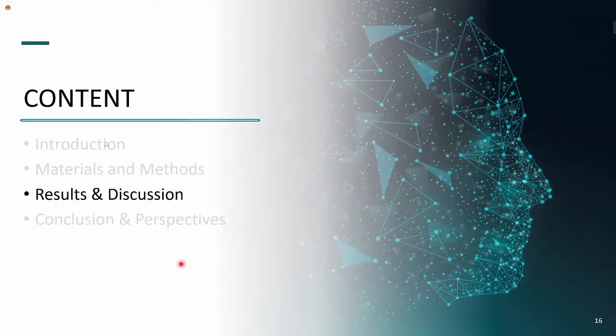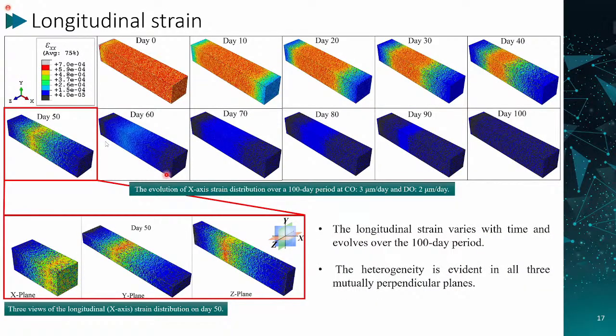So with this model, after applying 1 megapascal tension force, let's look at what we got from this model. This figure shows the evolution of the epsilon xx strain distribution over a 100-day period at such growth rate. We can see the longitudinal strain varies with time and evolves over the 100-day period. We just zoom in on the day 50 results, the 3 perpendicular cross planes. We can see no matter which plane, the heterogeneity is evident in all 3 planes.